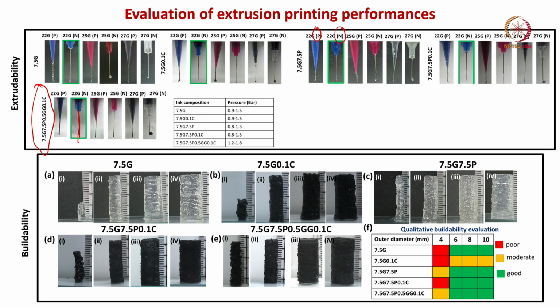And you can notice that in the case of the unreinforced GELMA, these different nozzle sizes do not give a very stable filament length and filament shape as required for establishing good printability of the hydrogel scaffolds.